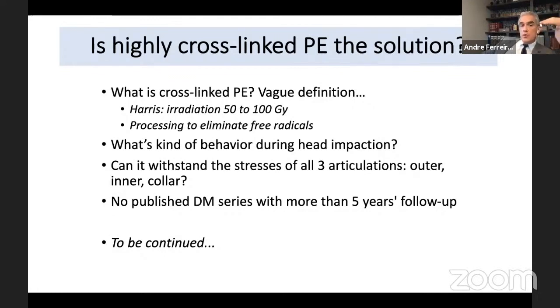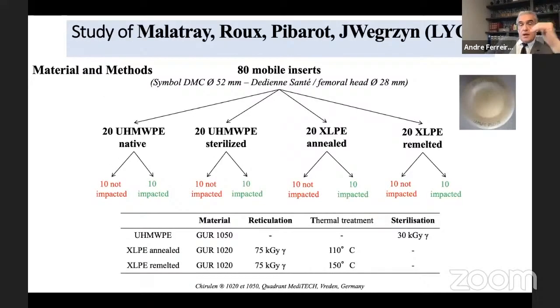And we have no published series with more than 5 years of follow-up with a highly cross-linked polyethylene. But there is another study done by Malatray, Roux, Pibarot, and JWegrzyn, published in International Orthopaedics too, and they compare mobile inserts with standard polyethylene and with highly cross-linked polyethylenes, annealed and remelted, with the insert impacted, the head impacted into the insert, or not impacted.